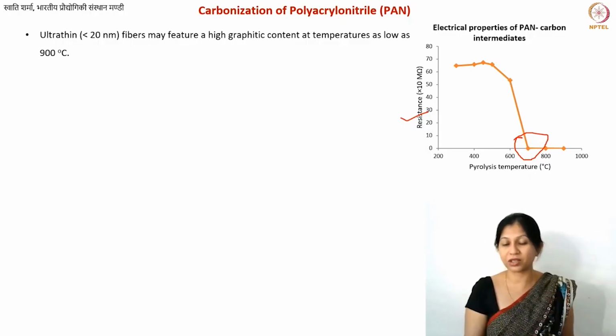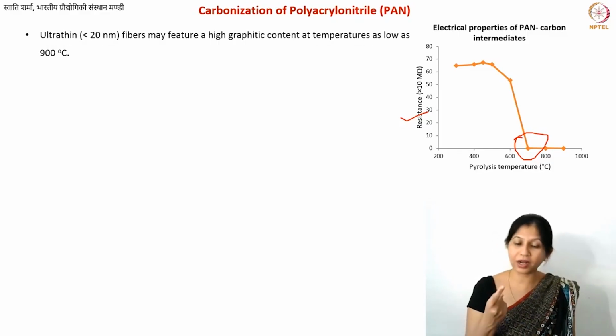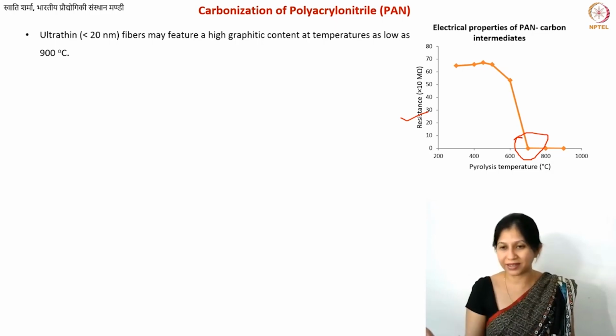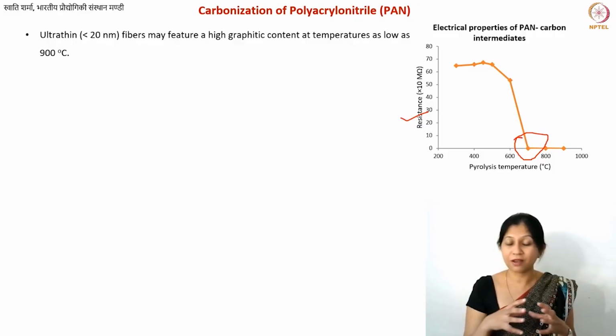So extremely small structures, if you carbonize them, they can have both byproducts and defects annealing out very easily, because of their high surface area. But as I mentioned, it does not happen in micro scale. This is often the case only at the nano scale, and especially fibers that are smaller than 20 nanometers. So in this case, you may get higher graphitic content at 900 itself.